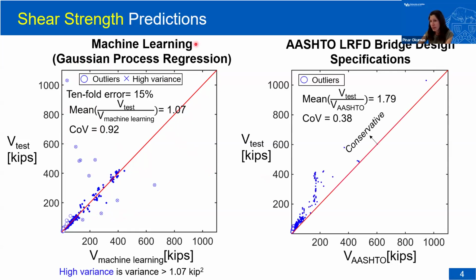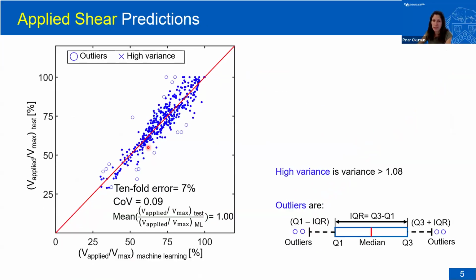If you wanted to compare that to how well design codes predict the capacity, this is one example. So this is AASHTO LRFD. You can see their mean of the ratio test divided by AASHTO is much larger. That doesn't necessarily mean that they're worse. They're trying to be conservative. That's the intent of the design codes. That's why all the dots are on the upper half of the plot. But it is an advantage to not have that conservatism in evaluation, because what's really valuable for new bridge design may not be needed for evaluation. And that's what our machine learning does.